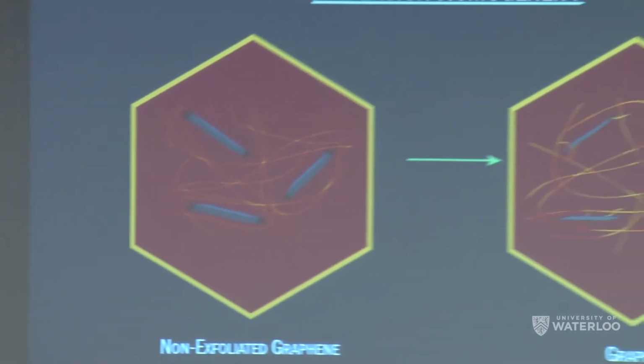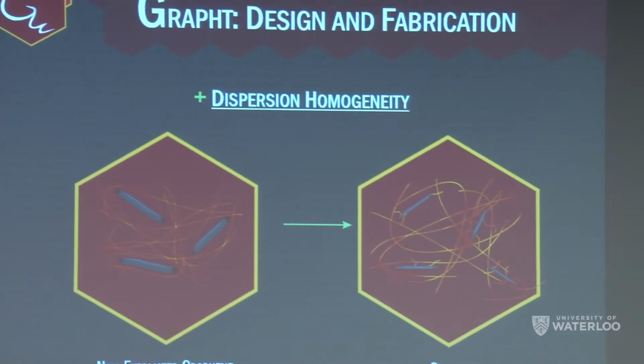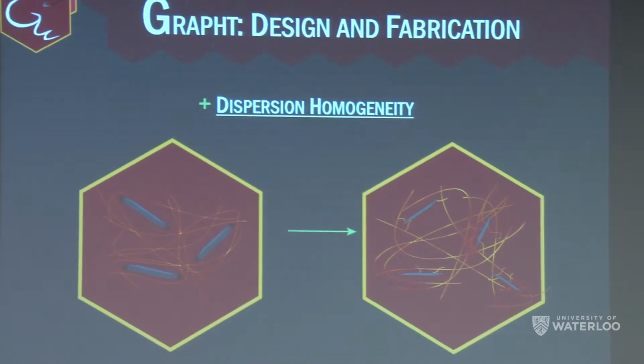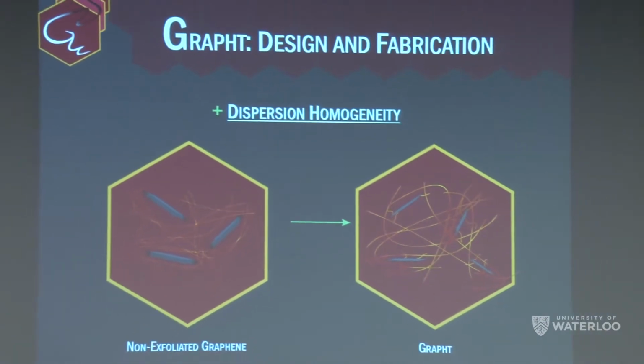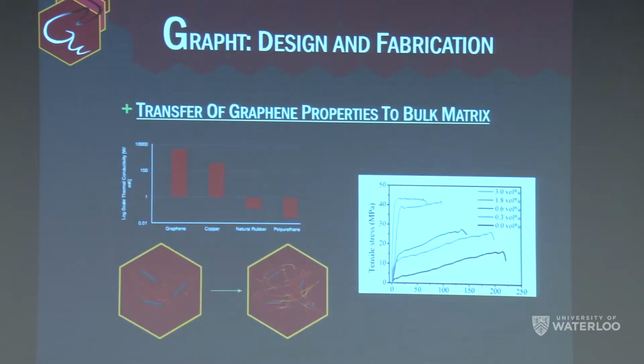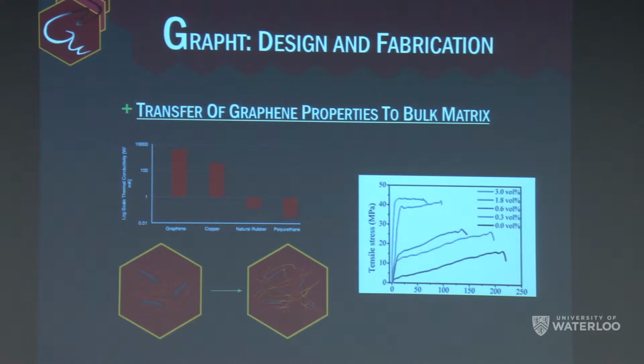Additionally, Grapht provides an improved dispersion homogeneity. With original graphene, when you put it into your compound, as Ricky said, it likes to clump to itself. It likes to stack up and form these agglomerated clusters. So you have to use high shear mixing, a lot of energy, to try and break it up, and even that doesn't usually get it all the way dispersed. This can cause you to have to add more graphene than you wanted to, and that's expensive because graphene costs quite a lot. With Grapht, it's been compatibilized so it likes to be in the polymer. It disperses far more readily when you mix it, and this directly leads into the transfer of the graphene's amazing properties to your polymer matrix.